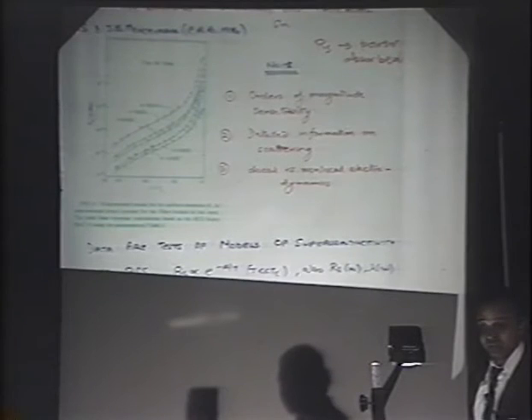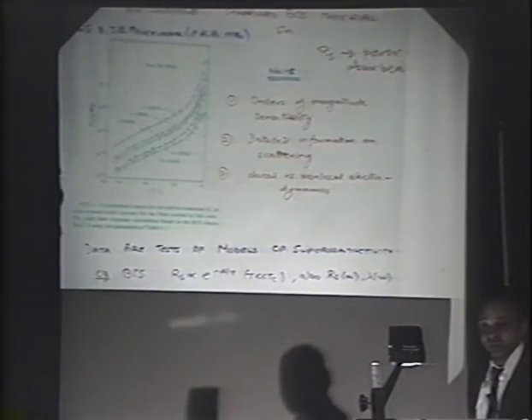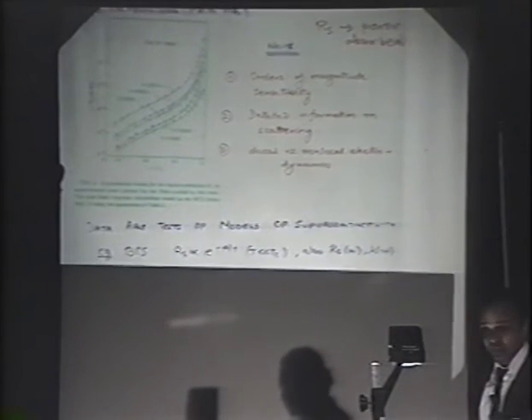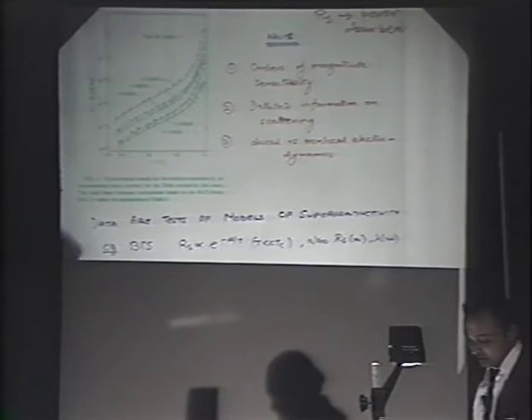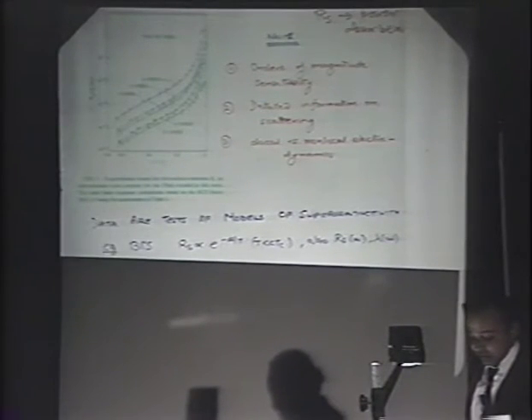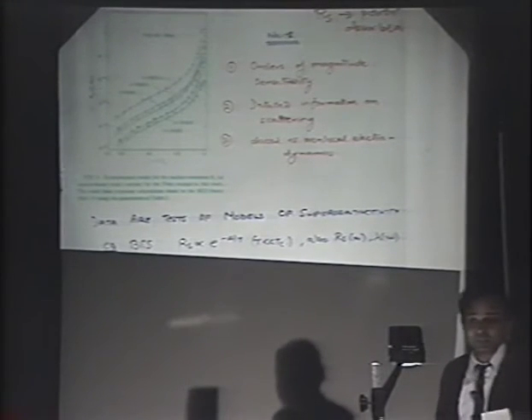detailed information on scattering, and also about more subtle aspects like local versus non-local electrodynamics. Conversely, data like this can be tested with models of superconductivity. For instance, in BCS, surface resistance is activated and decreases exponentially at low temperatures, and there are also specific predictions for the surface resistance and penetration depth.